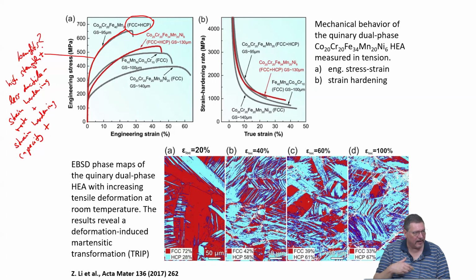And this is lying then in the microstructure, and in this case there is also a TRIP effect because the martensite is formed during the deformation, and this is what's adding. Why is actually a phase formation helping? Absorbing shocks. They transform to martensite. They are absorbing shock, TRIP effect.